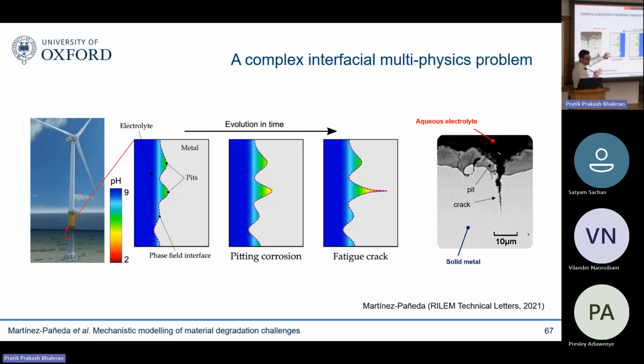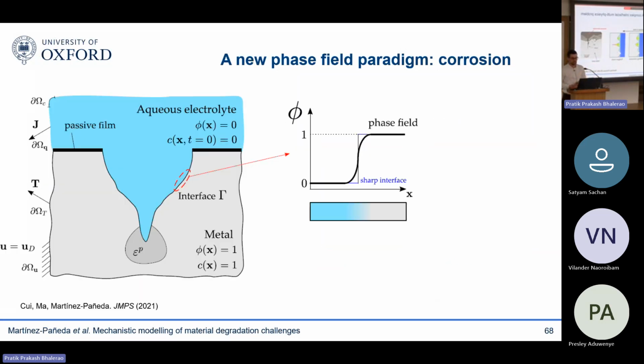But again, a coupled multi-physics problem and an interfacial problem. So why not use phase field for this? And if you think of the simple phase field description of corrosion that you're interested in, we no longer care about cracks. Now the phase field is going to tell me whether I'm in the electrolyte or in the corroded metal, and it's going to vary smoothly in between. And then you need an extra variable, which will be the concentration of metal ions, which will be equal to 1 in the normalized way in the metal and 0 far away in the electrolyte. So you generate those metal ions, and that allows you to capture the interplay between activation and diffusion control corrosion.